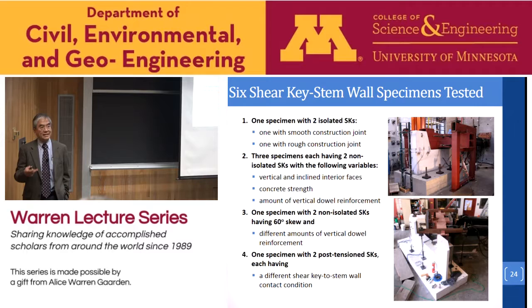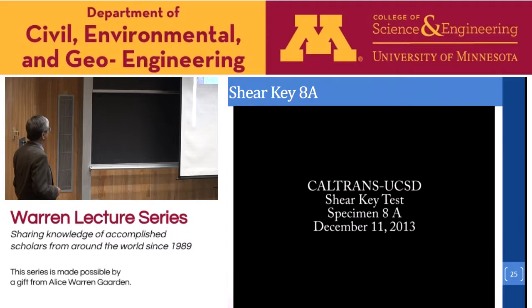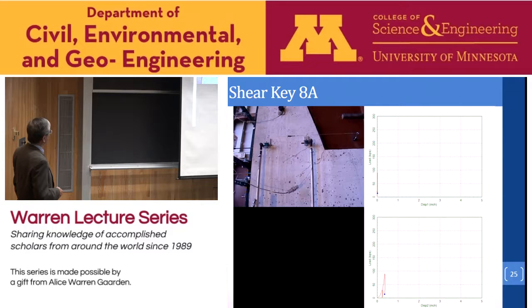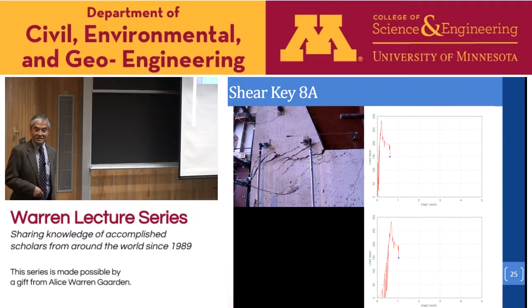And finally, we look at the more innovative design, a concept called post-tension shear key, never been used before. The idea is to let the shear keys rock instead of having fracture and sliding. So I just show you a test of a monolithic shear key that we achieved together with Caltrans engineers. We developed a design which could achieve the sliding failure instead of a diagonal crack propagating.